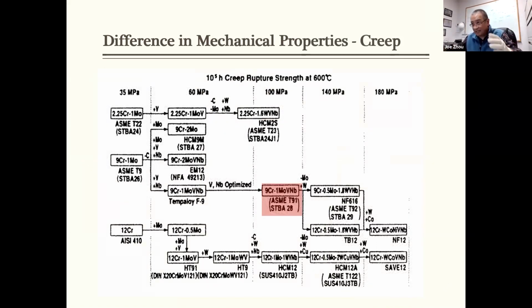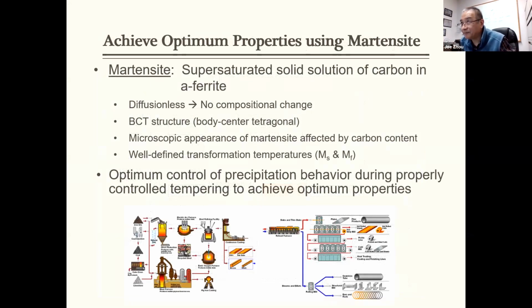So this slide gave you, you see what the 22 is. The 22 creep stress at 600 Celsius is only 35 megapascal, and the 91 is 100. Because you're changing the alloy system, you create a different microstructure, then you get a different level of mechanical properties.